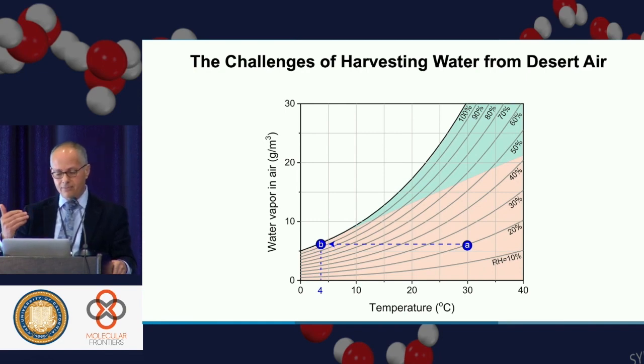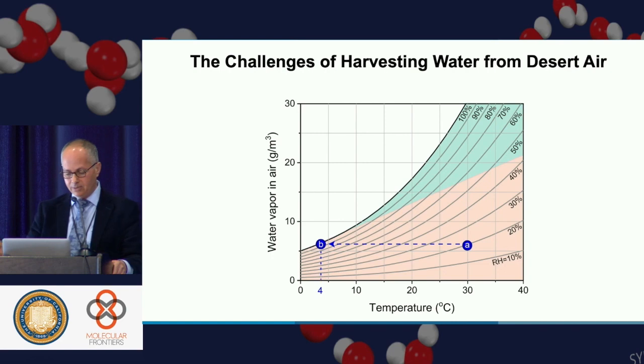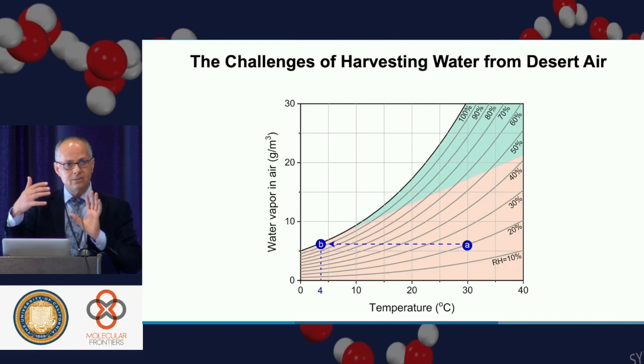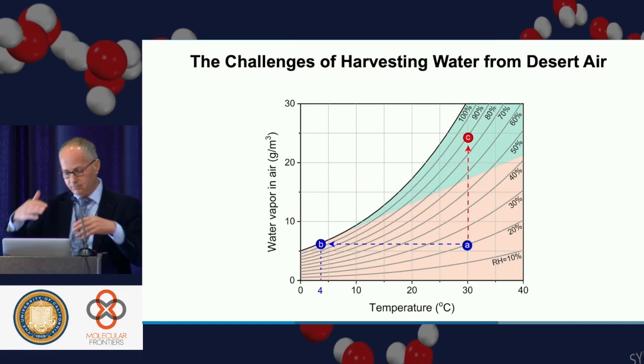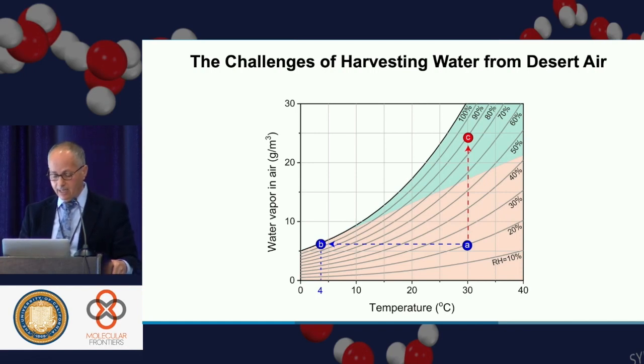So the way the MOF would work is that the pores that I have been describing to you could be tailored to pluck out water from the air, concentrate it into the pores. And in a closed system, I would basically make a humidified atmosphere. Okay, so that water that's stored in the pores humidifies the box or wherever they are contained. And now to get the water out of there, I only need to cool down by a few degrees. Okay, so in essence, what I'm doing is I'm taking desert air and turning it into tropical air. That's really the principle by which the MOF works.